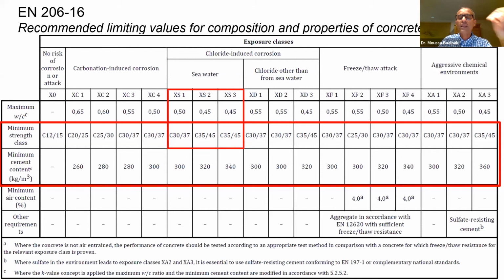Even though from a structural point of view, 25 megapascal is enough, due to the fact that you have an exposure condition with a certain severity, you need to increase your design to 37 megapascal. If you go, for example, to XS2 and XS3, this is either submerged in water or in the splash zone. You see the strength is 45 megapascal. Even though probably 35 megapascal or 30 megapascal would be enough, this is not the case. You have to take into consideration the exposure condition.